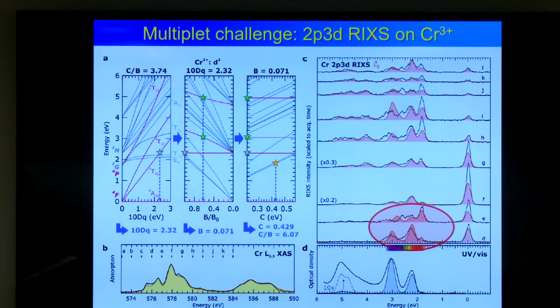Because it's extremely difficult, because this ratio between the Racah parameter C and B, or the ratio between Slater integrals F2 and F4, is completely different from an atom. So the solid is completely modifying the electron-electron interactions. And then as a last example is